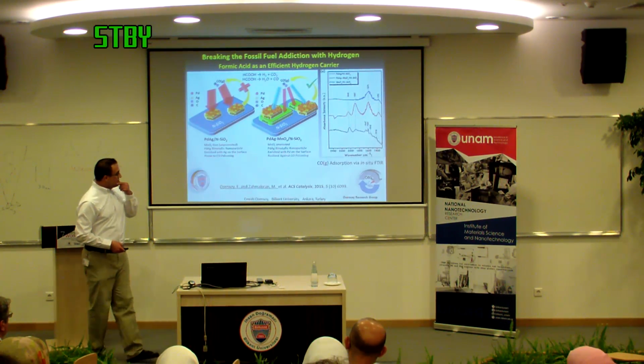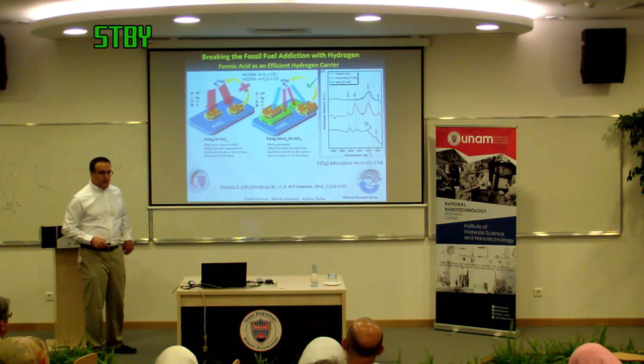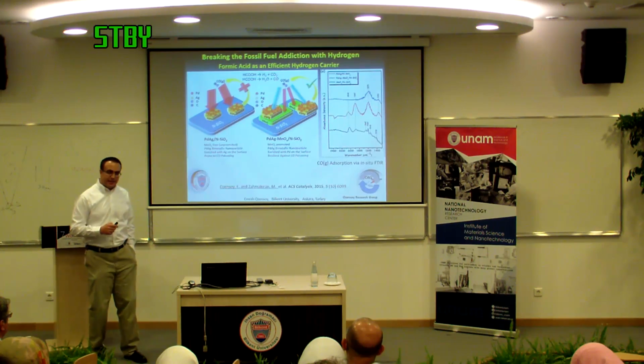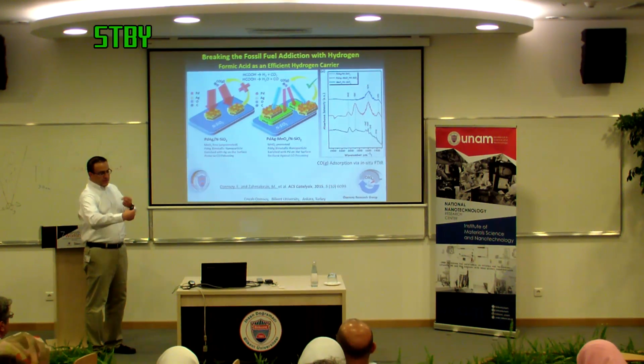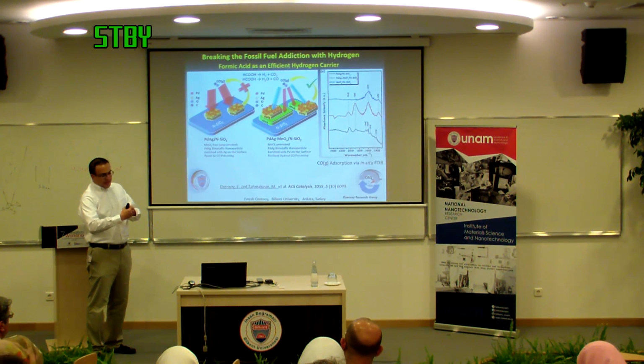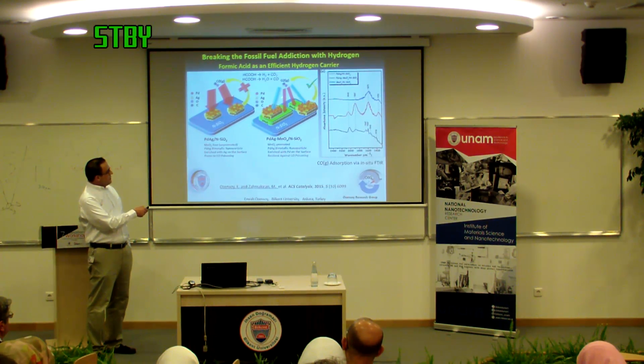So we have done a bit of spectroscopy on these things, and we have verified the following. If you take palladium, the active site, and blend it with silver, a very small amount, less than 10%, and make a bimetallic catalyst, the poison CO doesn't adsorb on this palladium-silver anymore. Silver changes electronically the d-electron states of palladium, and it donates electrons to CO into the anti-bonding orbital, and you loosen the CO bond and also the palladium-carbon bond. That means you decrease the affinity of CO to the active site.